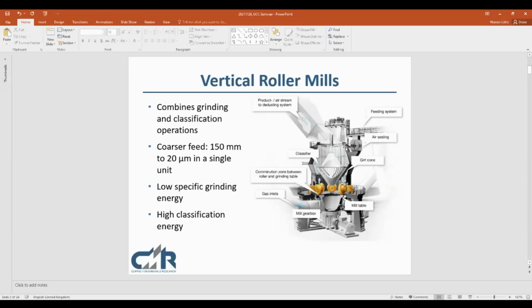The devices are commonly used in cement and coal grinding applications. And in these applications, they are accepted as being more energy efficient. The dry grinding applications, they are more energy efficient than conventional tumbling mills. So the increased energy efficiency there is coming through from the lower specific grinding energy. We have a direct application of force from the rollers to the particles, unlike conventional mills where we have energy transfer to steel balls, which then fall. We have a lot of excess energy wastage, so direct energy transfer here.